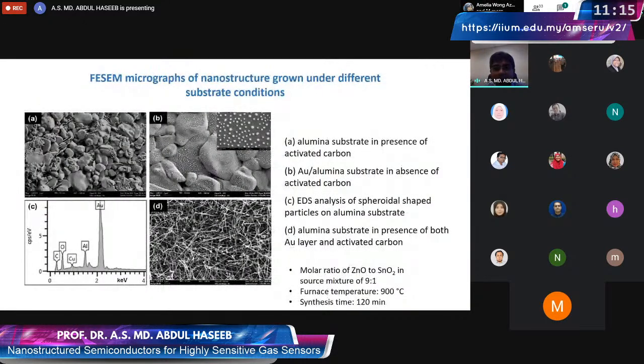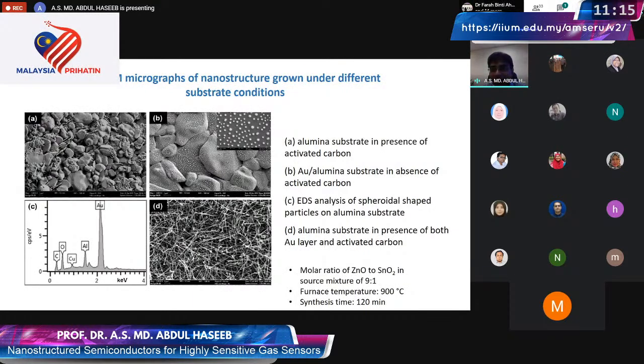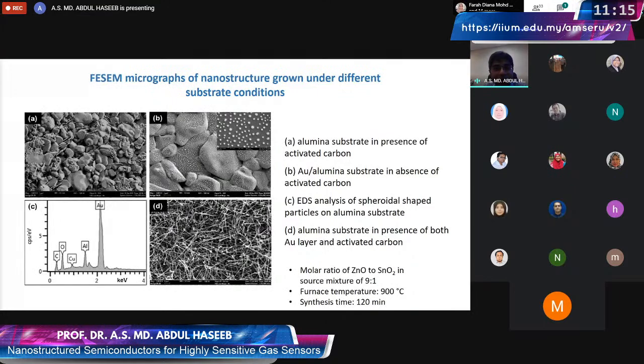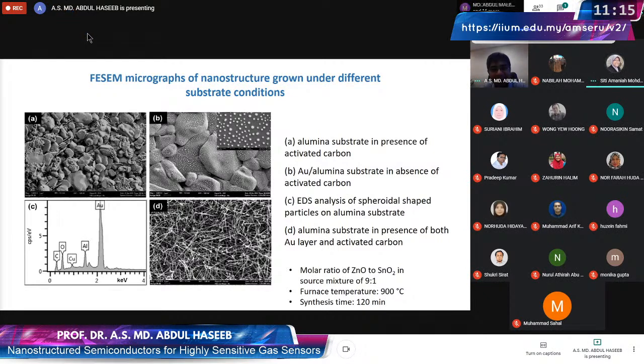Let me show you. I think I have one slide which I quickly skipped over, showing what happens when we do not mix carbon. Can you see? Yes, I can see. If you look at B, we did not use activated carbon in the mixture, and what we see is that there is no nanowire. We just see the initial gold layer becoming gold islands, which is normal at high temperature. But the nanowires cannot grow because we do not have the supply of zinc from the boat. In order to get the supply of zinc, we have to reduce the oxide and create zinc vapor, which will come over to our substrate. Is it clear? Yeah, okay, thank you. Very interesting presentation. Thank you very much.